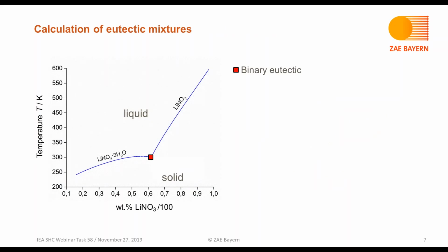So for the first step, the calculation of eutectic mixtures. Why are we doing this? Here, a simple phase diagram is shown in the figure. To keep it simple, the line illustrates the solubility threshold, the transition in temperature between the liquid and the solid. Above the line, everything is a liquid solution, and below, different solid phases precipitate. As marked here in this system, lithium nitrate and water, there's a binary eutectic, and this is interesting to be used as PCM.